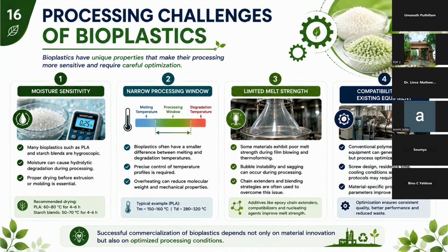So if a film is extracted from the machine, we can check the water contact angle. If the angle is less than 90 degrees, it seems to be hydrophilic. If the angle is more than 90 degrees, it is hydrophobic. So that has to be considered. That determines the feature of the polymer.